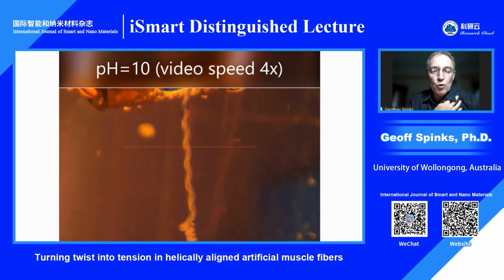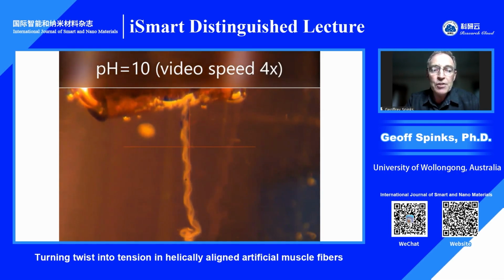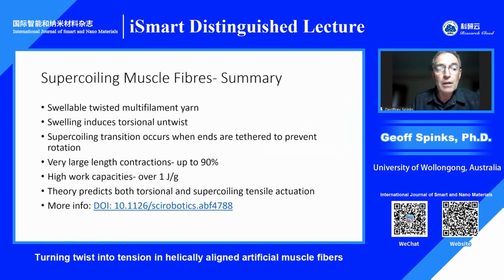The torsional energy generated in these swelling fibers is just too great, and it becomes energetically favorable for them to form these loops and supercoils. So in the supercoiling study, we were using multi-filament yarns that were swellable. And as with every other system, the swelling would induce a torsional untwist if it was left on its own. But if we tether the ends to prevent rotation, in these cases, we can tune the elastic properties of the fiber to encourage supercoiling. So we've developed some models around this process.